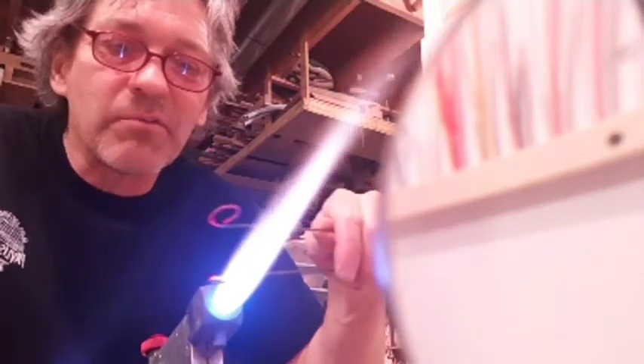All right, I'm going to get this little tweezer I've made, heat it up. So the metal is orange, and then when it goes to black, I'll give it an extra second, and it'll be at the right temperature to pick up that marble without shocking the surface. Then, we can look at it quickly. It's a marble! Yes, that's what we were doing here. I'll put it in the annealer.